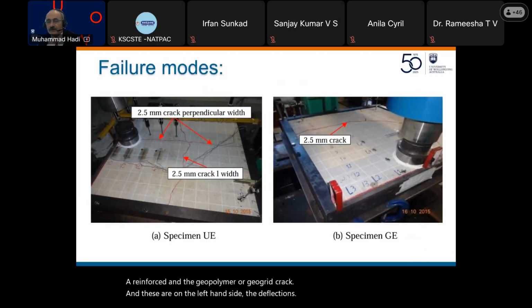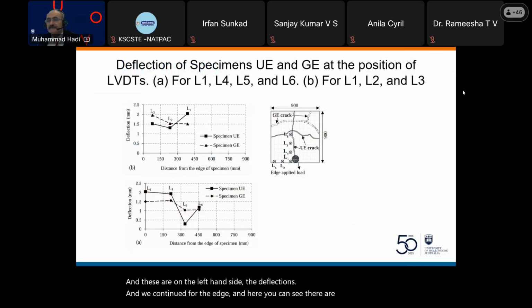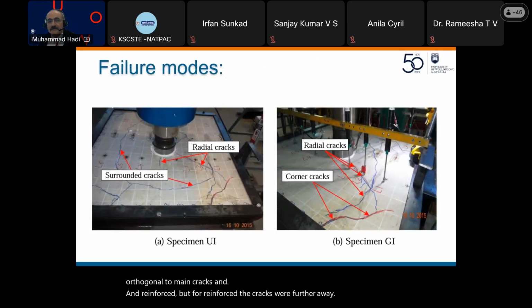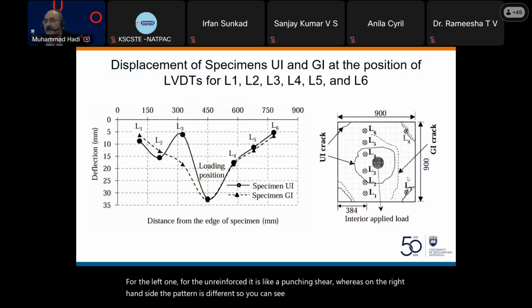And we continued for the edge. And here you can see clearly the cracks are orthogonal to main cracks for the unreinforced, but for the reinforced, the cracks were further away. And the last one was the interior. The left-hand side is the unreinforced, the right-hand side is the reinforced. And you can see for the left one, for the unreinforced, it is like punching shear, whereas on the right-hand side, the pattern is different. So you can see the cracks are different here.